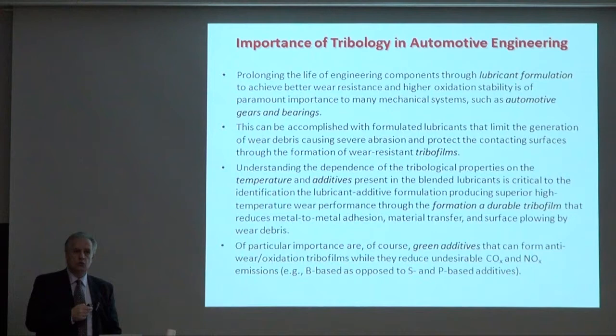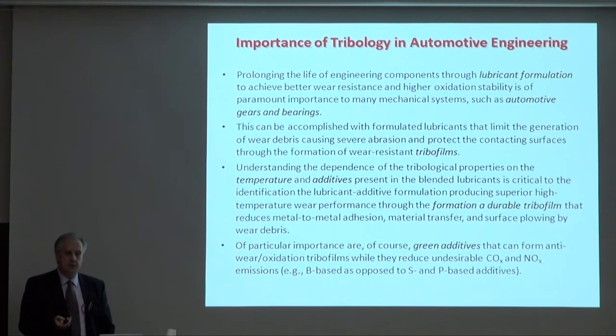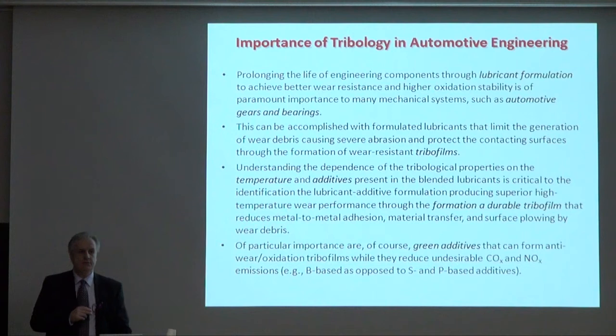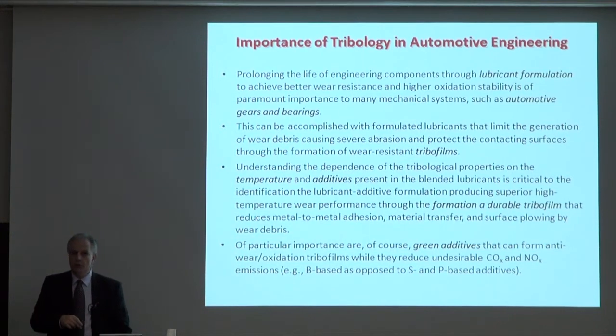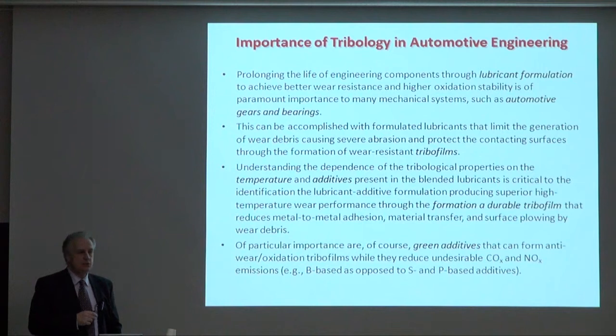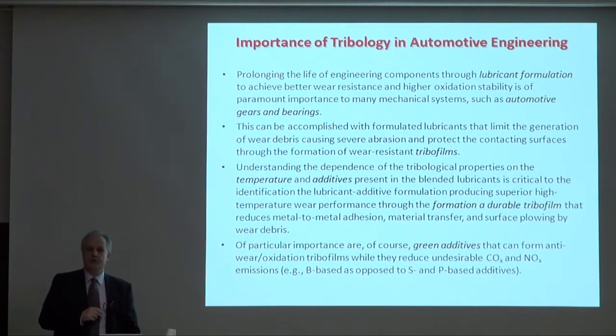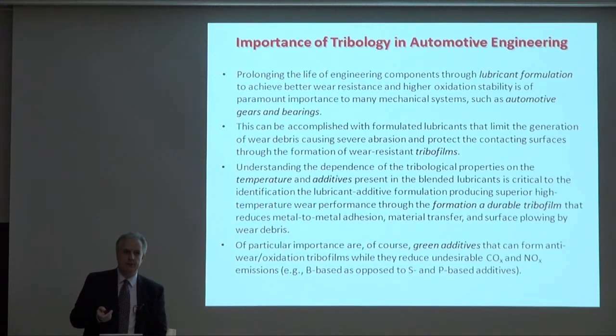The role of the additives is to immediately intervene and reform it everywhere on the metal surface that has been removed. So you understand that there is a continuous affinity of the surface for these additives that are broken up and activated by the rubbing process to strongly adsorb on the exposed metal surfaces every time that the tribofilm locally is removed. It's worn off. So that process, therefore, leads to a continuous reformation of the tribofilm, and that's why it is referred to as sacrificial film, because it sacrifices itself for the sake of protecting the precious engine metal underneath.